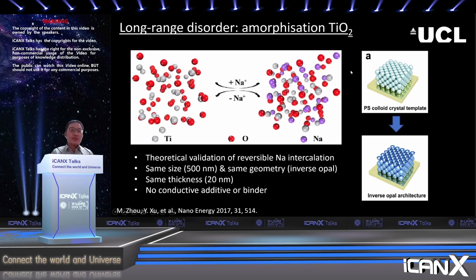Back in 2012, I discovered that titanium dioxide is a good material for sodium-ion batteries. I did this work at the University of Alberta in Canada, where this was the first work of using titanium dioxide for sodium-ion batteries. It has been 8 years since that work was published, and I've seen hundreds of works on titanium dioxide, not only for sodium, but also for lithium and actually for potassium very recently. But they all focused on the crystallized titanium dioxide.